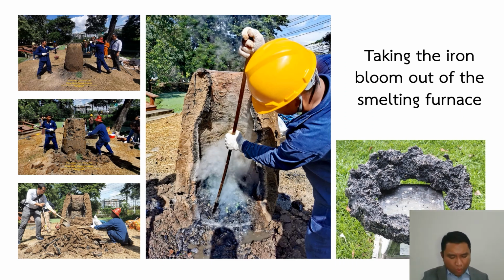Next, we took the iron bloom from the furnace after 4.5 hours. The research team found that iron bloom had accumulated and clogged the aerator. Then we finished the smelting process and broke open the furnace to bring out the bloom of iron.